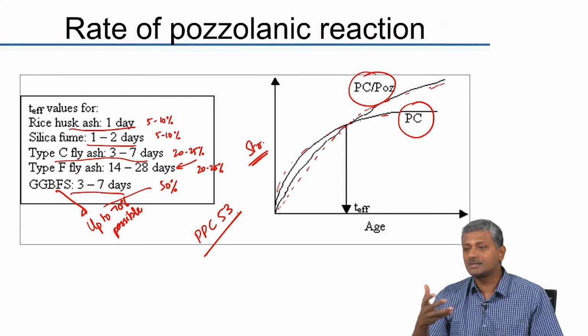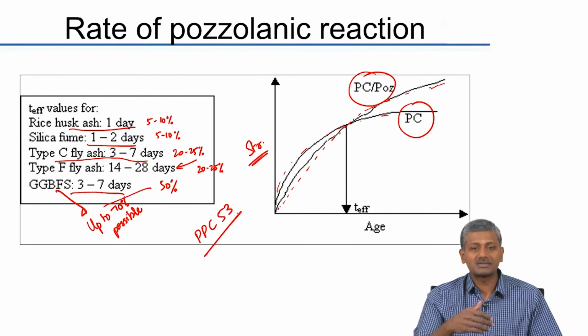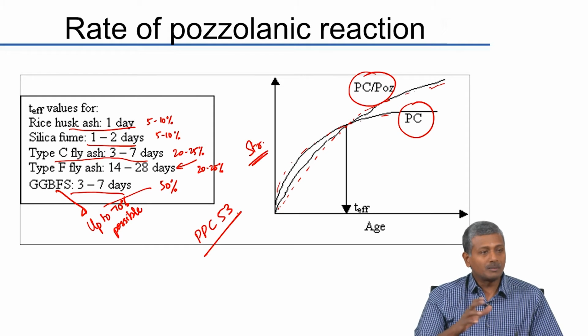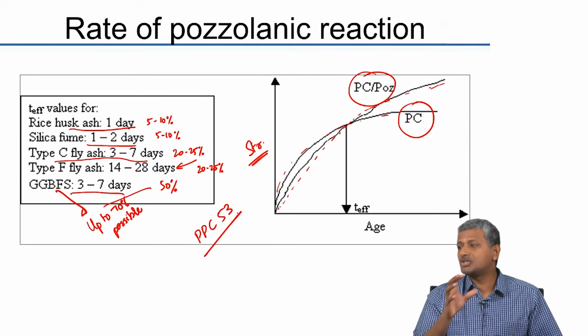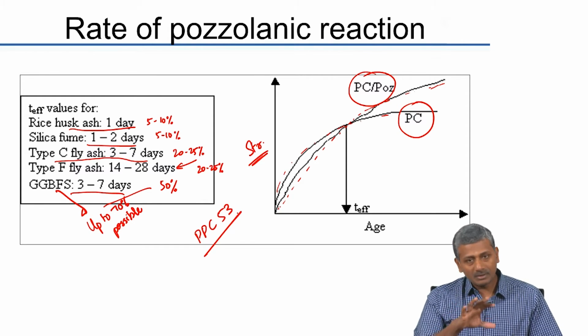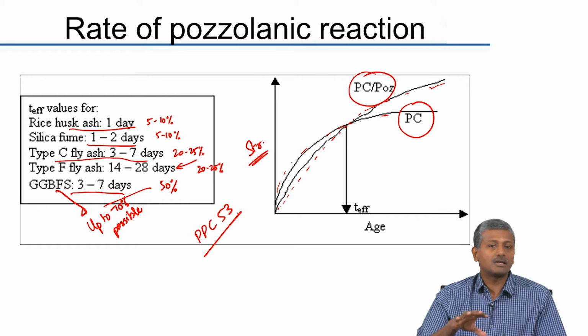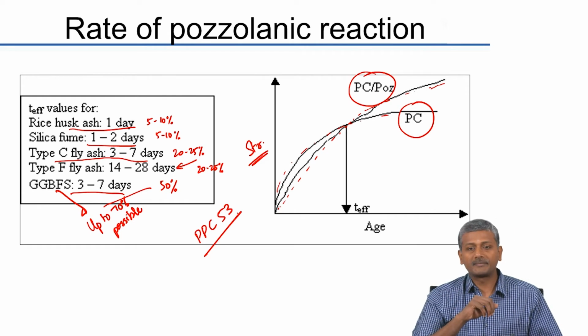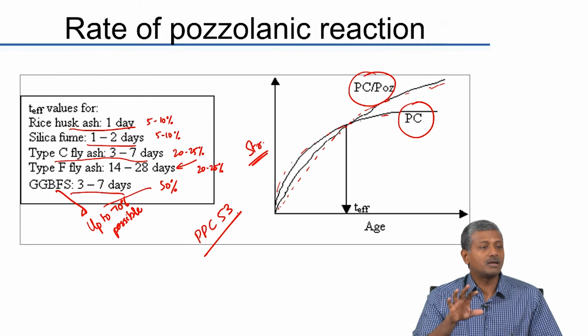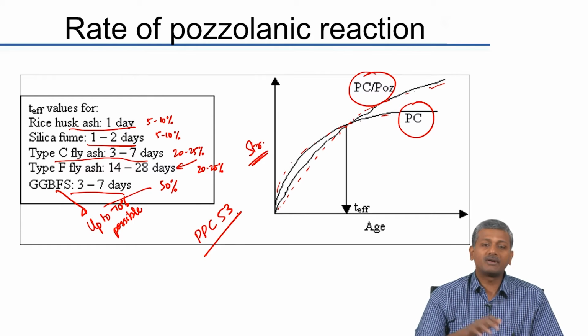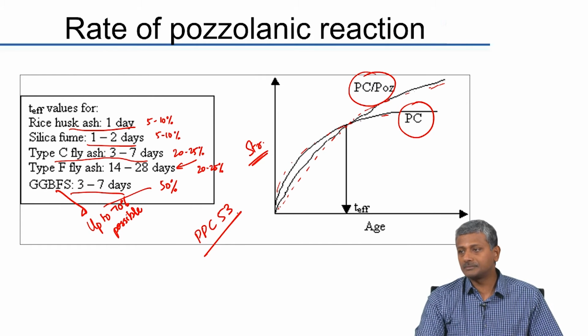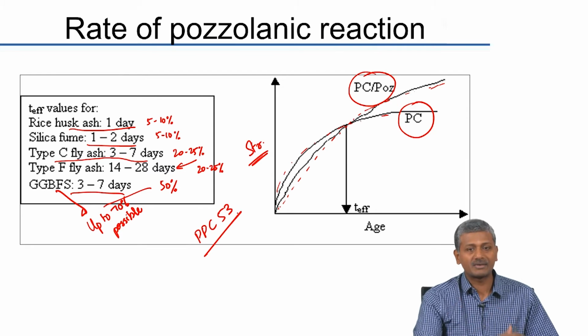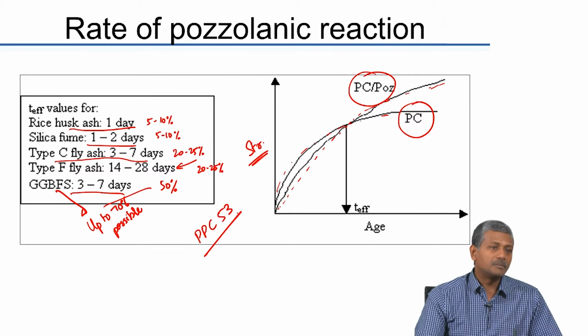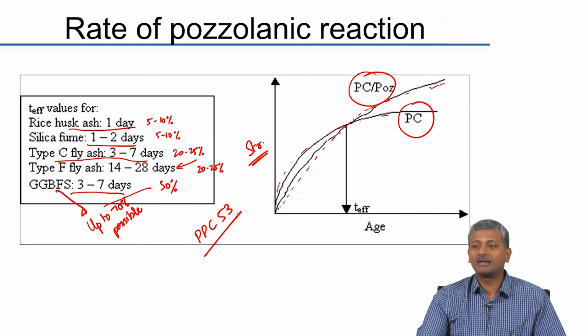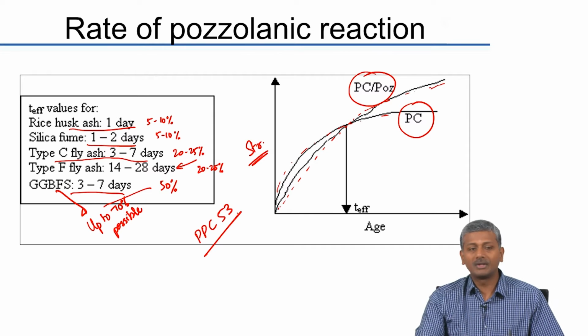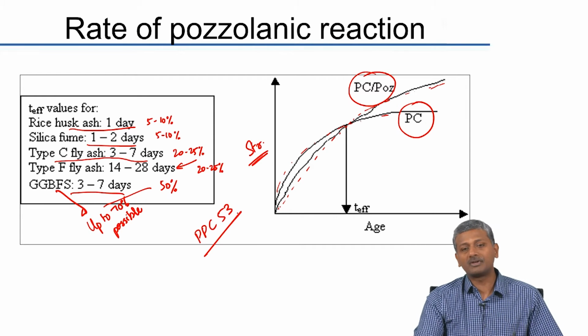So, because of all this, cement companies realized their folly and started coming back to a little bit more conventional PPC, even though they still grind PPC a little bit finer than cement. Okay, they grind PPC to the level of about 330 square meters per kilogram, where regular cement is about 280 to 300. So, some level of increased grinding is still there, which may help, but too much finer grinding will lead to more problems for storage, and you are not really getting the best benefit out of these cements.